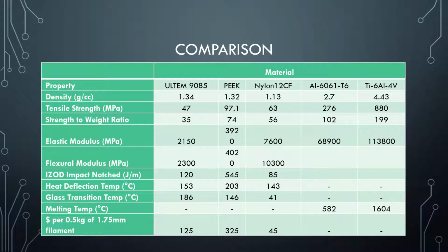Carbon fiber reinforced nylon 12 is much more affordable and can be purchased for $68 for 0.75 kilograms, or equivalently $45 for half a kilogram of 1.75 millimeter filament. While nylon exhibits excellent fatigue characteristics, it struggles with high moisture absorption rates. To compare all three, look at the following table. In this particular comparison, note that polymer properties are for printed FDM material. Metal properties are from stock material, not metal AM results.